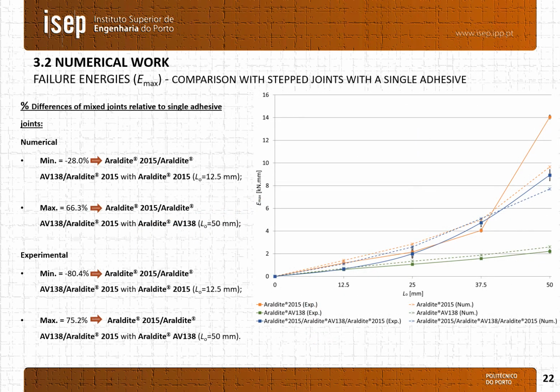Performing the failure energies comparison of the dual adhesive relative to the single adhesive, in the numerical analysis, the minimum difference observed is minus 28% in regard to the adhesive Araldite 2015 and an overlap length of 12.5 mm. The numerical maximum difference is 66.3% when compared to the adhesive AV138 and for an LO equal to 50. In terms of the experimental results, the minimum observed difference is minus 80.4% regarding the adhesive Araldite 2015 and overlap length of 12.5 mm. The maximum experimental difference is 75.2% when compared to the single adhesive AV138 and an LO equal to 50 mm.